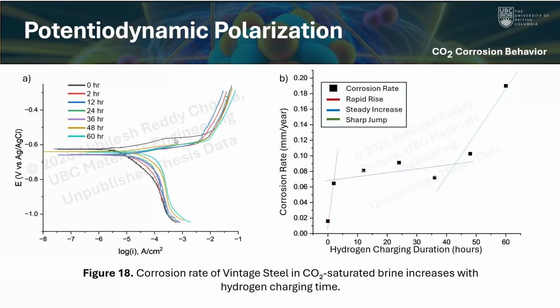And what I found was, right when I removed the steel samples from the charging electrolyte and immediately placed them in the CO2-rich solution, I saw that the charge transfer resistance decreased as I increased this charging time. So that also tells me that before I apply any positive potential to oxidize the steel, right around the open circuit potential, the natural potential of that steel immersed in solution, we see that the steel is willing to give up an electron, or oxidize itself.